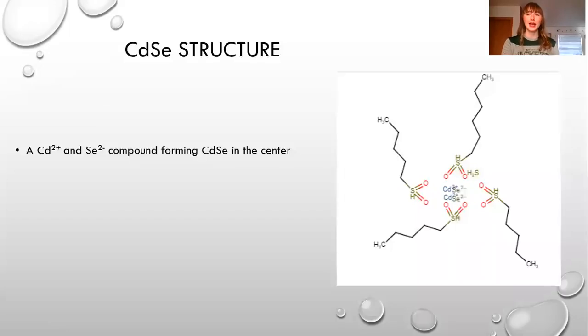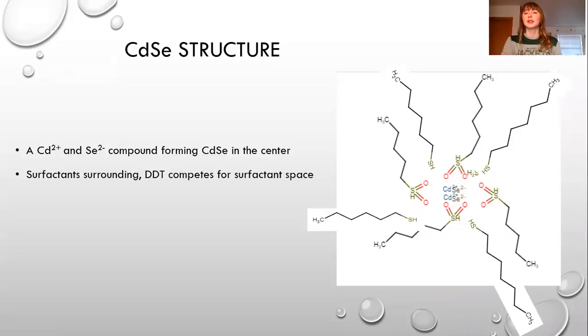So what does this actually look like and how does it work? In the first part, before we add DDT, these surfactants, these kind of tail things, surround this quantum dot in the middle. And these are being pulled off when we actually do our research, but I'll show pictures of that later. So when we add DDT to this, it adds another surfactant that competes for space around the dot. And this competition, in theory, apparently shrinks the size of the quantum dots as we've seen in the data.